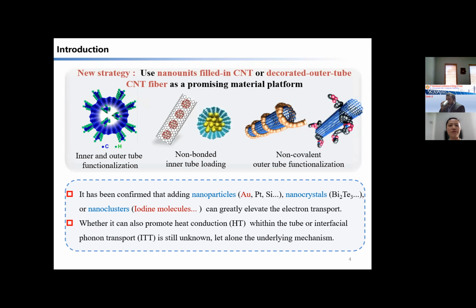We can use nano units filled in the tube or decorated on the outer tube fiber as a promising material platform, such as inner and outer tube functionalization, non-bonded inner tube loading, non-covalent outer tube functionalization, and so on. It has been confirmed that adding nanoparticles such as gold nanoparticles, nanocrystals, or nanoclusters, iodine molecules, the red color material is our focus, can greatly enhance the electron transport. However, whether it can also promote heat conduction within the tube or interfacial transport, and the underlying mechanism, that's what I study.